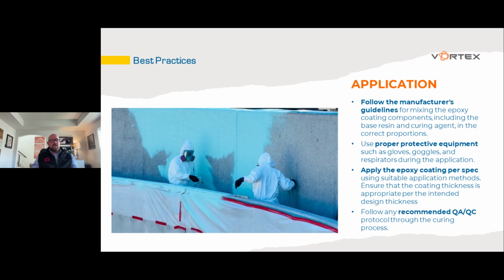Once we've got that surface prepped and we've followed all of those guidelines, now we can get to the application side of it. Application of these materials, whether that's in a wastewater treatment facility or in a manhole, needs to be properly adhered to. So we're going to ask that you follow the manufacturer's guidelines for mixing the materials, and that includes what equipment it's mixed in, at what ratios, and at what temperatures as well. Those proportions, temperatures and equipment are key to the proper installation of the material.